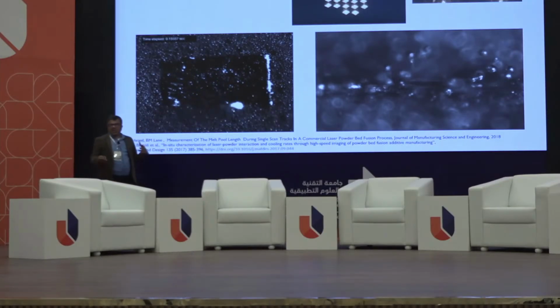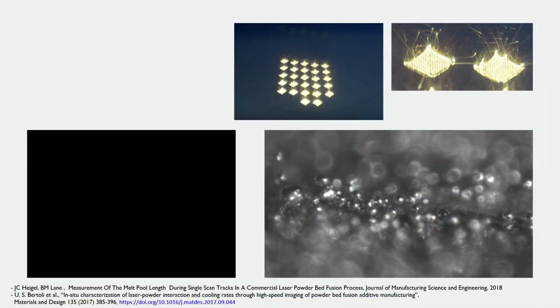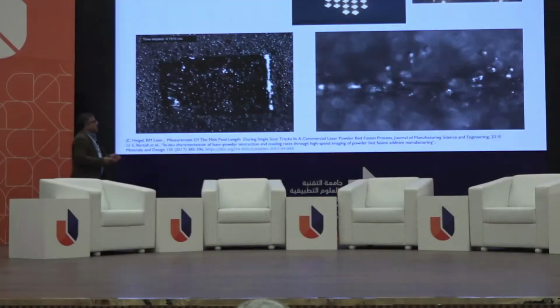There are techniques that can be done to reduce this effect, but not to avoid it. One of them is to supply more powder. So if I'm printing in 90 microns, I supply powder enough for at least twice that, so 180 microns. But the layer is already adjusted to 90 microns, and the mechanism will push them away. Yeah, and then I can also reduce it by optimizing the gas flow rate.